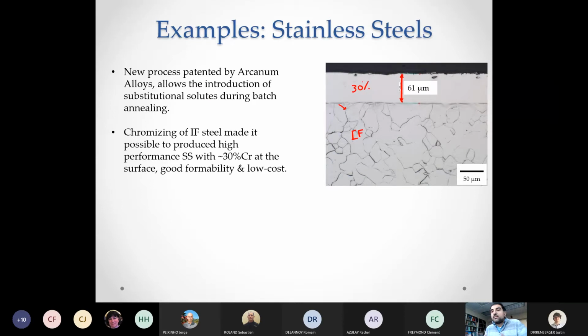So as a result, this could be used as an alternative to stainless steel in some applications. And it can actually compete very strongly with stainless steel because 30% chromium, only the most expensive stainless steels have that kind of chromium level. And then they don't have great ductility, but this material has great ductility because the inside of the material is an IF steel, which is very soft and very easy to form. And the cost is a lot less than the cost of the stainless steel because you only need chromium near the surface.